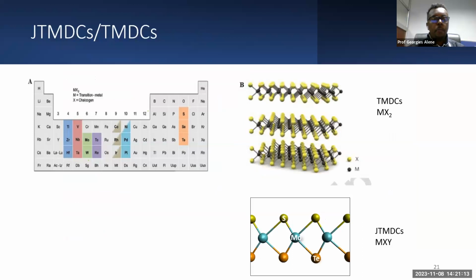in the next slides. So first, we can define transition metal dichalcogenide. Maybe it is obvious, but it has MX2 stoichiometry, where M is a transition metal and X is a chalcogen. So the transition metal you can get from the periodic table, and if you combine it with a chalcogen, usually sulfur, selenium, or tellurium. So if you combine one transition metal with two sulfur, for example, you will get MS2. Then that is a transition metal dichalcogenide. And usually they have a layered structure, so they are 2D materials, and it is easy to exfoliate them because the planes are connected by a weak van der Waals interaction. So it is easy to exfoliate and to get 2D materials.